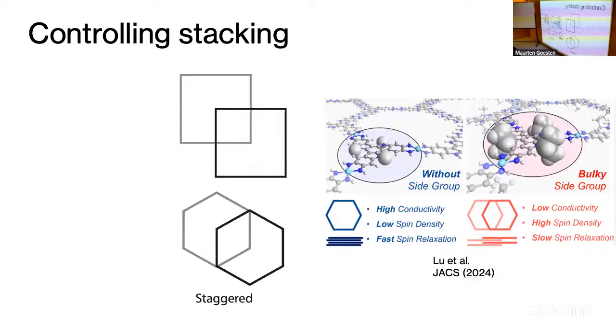So for instance, these MOFs are being explored for quantum computing. This is Xinliang Feng's group, Max Planck in Dresden, who are maybe the best in the application of these frameworks for those purposes. So they're really doing amazing work. But what you can see is that they enforce a staggered stacking to lower spin lattice relaxation rates. And you don't always want to have eclipsed stacking. It's not that simple.